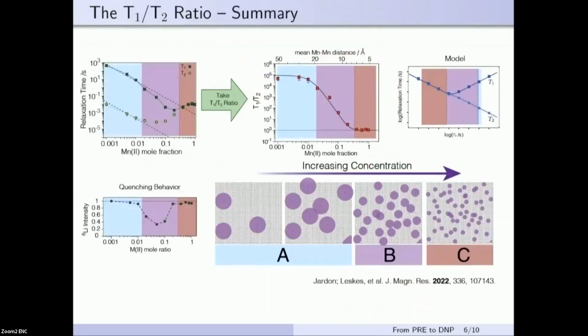So to summarize this and connect it to the quenching story: at the low concentration regime, we have a very long electron relaxation time. In the BPP model, it puts us on the far right side of the figure, meaning that nuclei in close proximity to the paramagnetic center will have an extremely short T2. This is equivalent to the quenching radius around each paramagnetic center being very large. Now we start increasing the concentration. At the beginning, we don't affect the electron relaxation time, but we increase the number of quenching spheres. So the signal intensity drops, which is what we were observing.